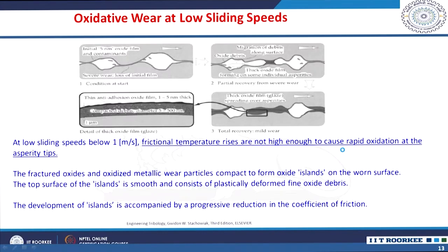Whereas, in oxidative wear at low sliding speeds below 1 meter per second, the frictional temperature rises are not high enough to cause rapid oxidation at the asperity tips. So, the fractured oxides, you will see the oxide debris, right? These fractured oxides and these metallic particles that are oxidized compact to form oxide islands on the worn surface, right?